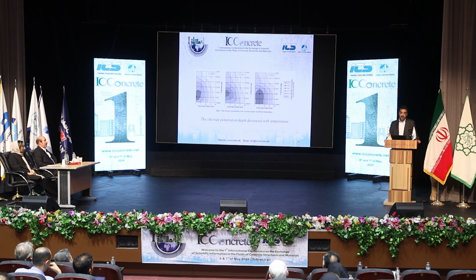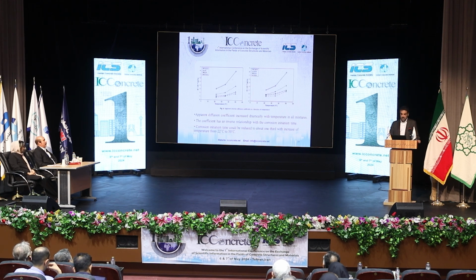As you can see in this graph, the depth of chloride intrusion in concrete was higher in higher temperatures. And also, the ambient temperature had an enormous effect on the chloride diffusion coefficient. The corrosion initiation time could be reduced to about 1/3 with increase of temperature from 22 degrees Celsius to 50 degrees Celsius. In other words, the lifespan of reinforced concrete in hot weather could be about 1/3 of countries located in moderate conditions.